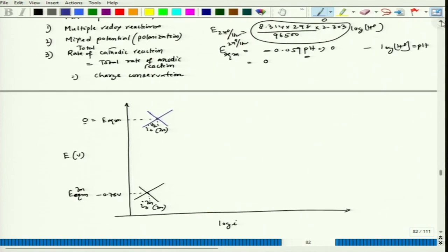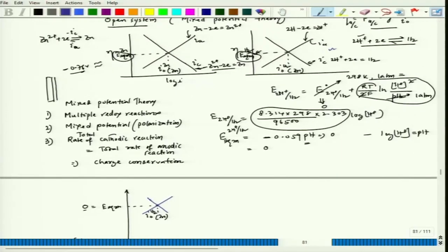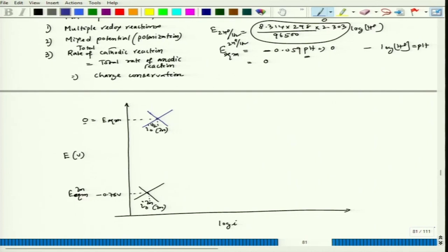Just like what we have done here. So, these two are put up here. Now, the system has to achieve a mixed potential where the total rate of cathodic reaction should be equal to the total rate of anodic reactions. And here we have two cathodic reactions and two anodic reactions.